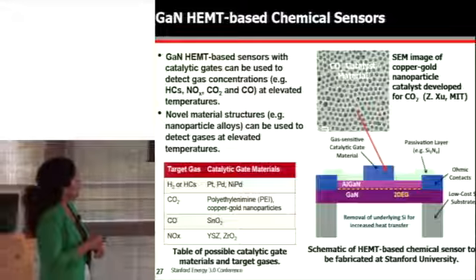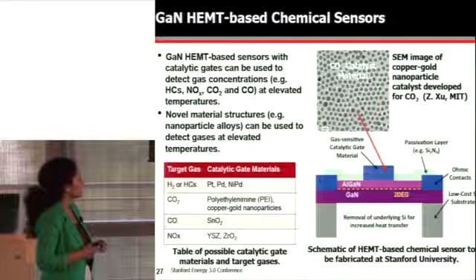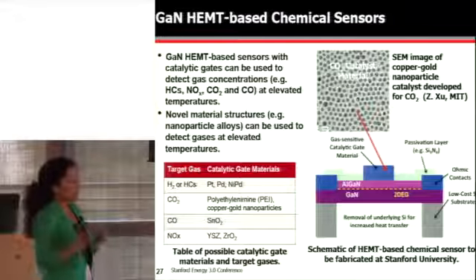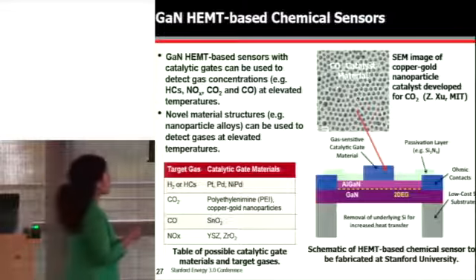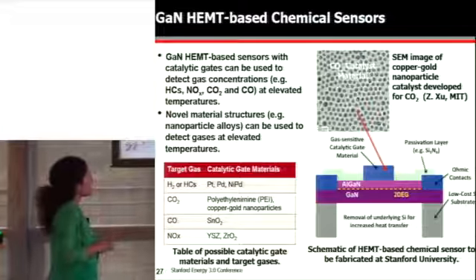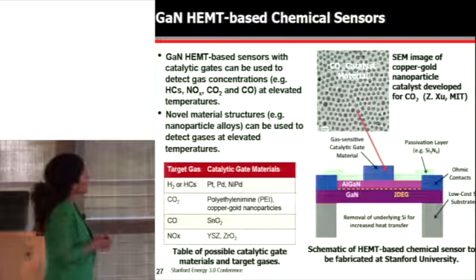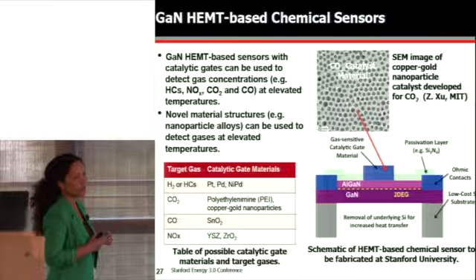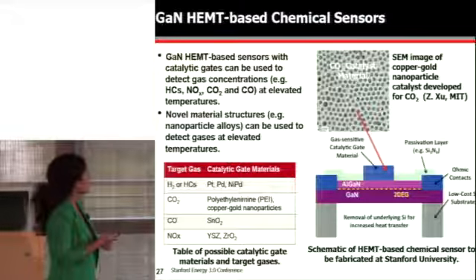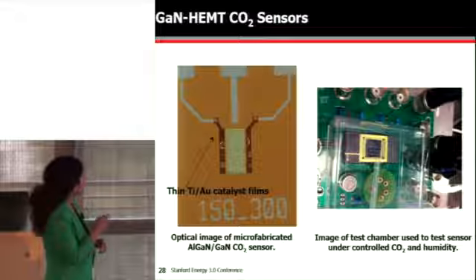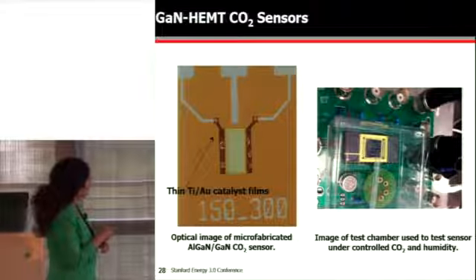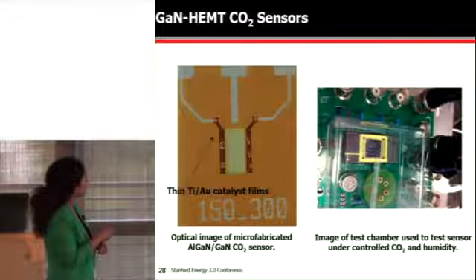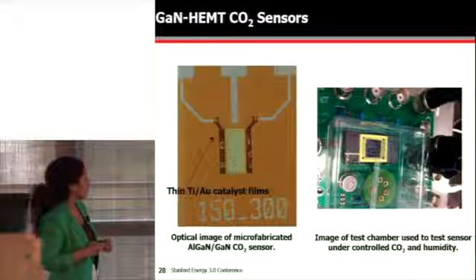If we change the configuration of the gate and position nanoparticles that are sensitive to different types of gases, for example, a nanoparticle-based catalyst, we can then think of creating new types of chemical sensors that can operate at high temperatures as well. And so we're exploring different types of chemical-sensitive gate materials to detect CO2. And currently, we're looking at copper-gold nanoparticles and then other types of copper-based particles. My student had a poster earlier today giving an update on that work. But this is an image of a gallium nitride sensor. We have the source, drain, and then the open gate with the gold titanium catalyst. And we're in the process of testing this device under controlled CO2 and humidity environments.